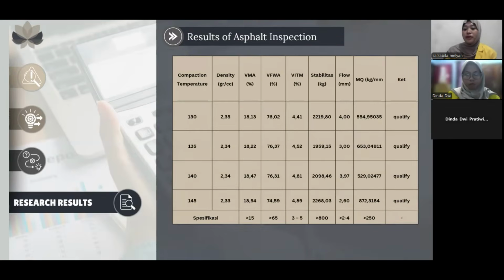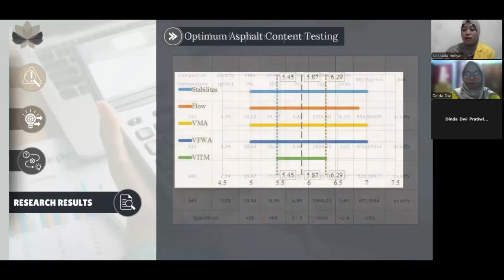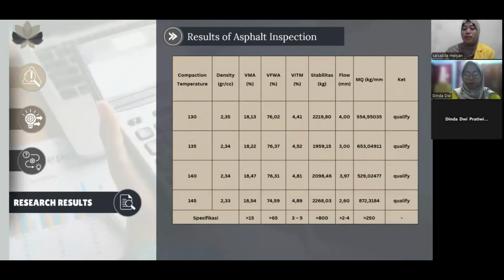We test different temperatures. At 130 degrees Celsius, the stability is 2,219.8 kilograms. At 135 degrees, the stability is 1,959.15 kilograms. At 140 degrees, the stability is 2,098.46 kilograms. And at 145 degrees, we get the best stability of 2,268.03 kilograms. Our temperatures pass the minimum requirement of 800 kilograms.